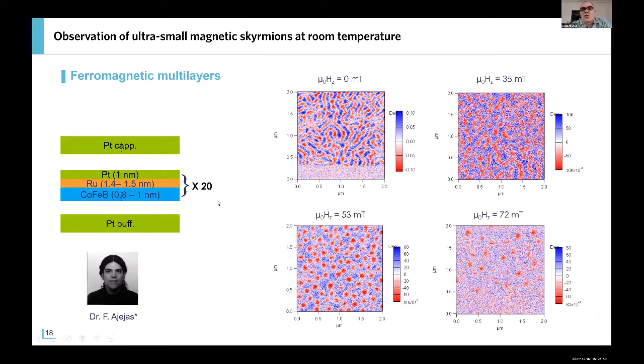And then we can repeat the number of multilayers of this basic brick in the multilayers. These are magnetic force microscopy images at room temperature. You see that at zero field you do have a labyrinthic state with up domain and down domain, and then if you apply a perpendicular magnetic field, you can transform this labyrinthic configuration into a phase or a regime where you do have a large density of skyrmions that can be stabilized.